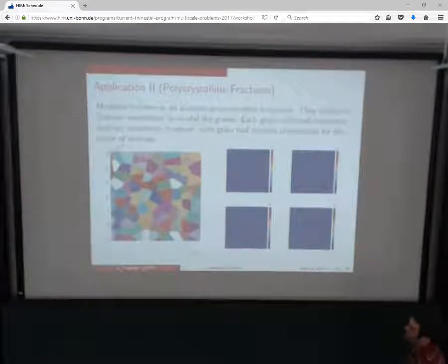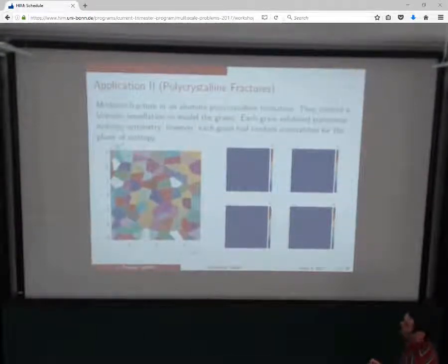Okay. They also had to define the bond function between the grains, and for that they just took the average of the two. And then lastly, they used the fracture energy to get the bond breaking criterion. They only had one constant, because it's probably not measured for the individual grain, I would imagine, but they had just one constant for alumina. So what they did is they had it defined for the interior of the grain, and then for the boundary bonds, they had to basically assume a ratio based on that one. So they would either assume it's weaker or the same.